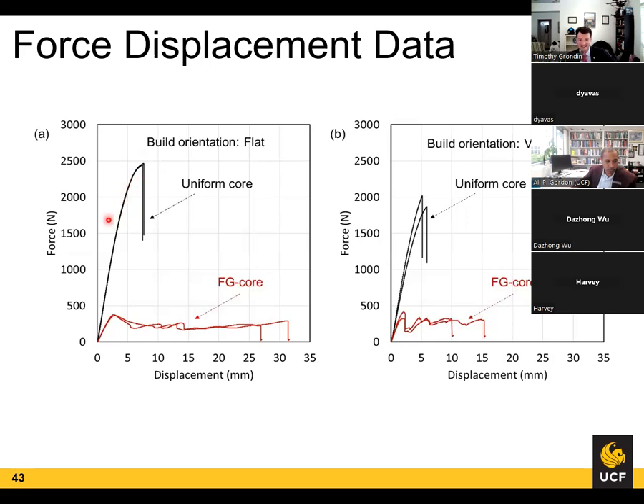We weren't expecting that based on the data sheet. Now, for plotting just our comparison with our FEA results, again, we only did 1 millimeter displacement in the FEA, so we extrapolated that out 5 times so you could see it. It's correlating pretty well with the data that we had here for the functionally graded core as well as uniform core, especially in the vertical build orientation, extremely close.